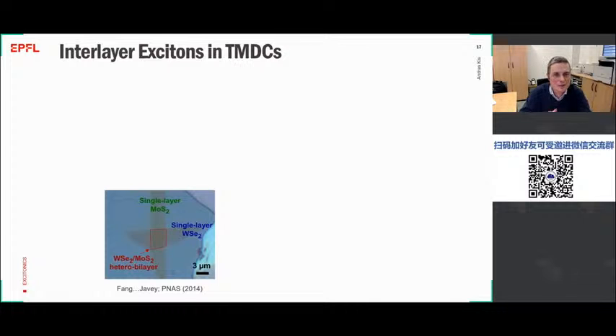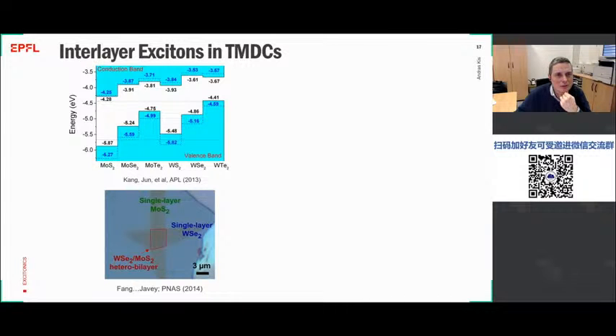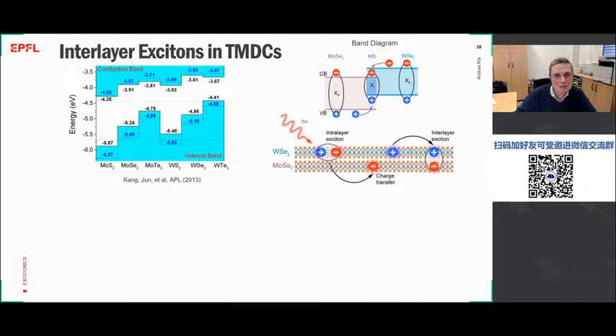In the case of 2D materials, this is very easy to do because the lack of dangling bonds on their surface means that we can take any one of those 500 or more 2D materials and put it on top of any other one of those materials. And when we do this, if we're talking about semiconductors, then we're also going to have, in certain combinations, different types of band alignment. And if we choose a combination of materials, like, for example, MoS2 and tungsten diselenide or MoSe2 and tungsten diselenide, then we're going to have a so-called type 2 band alignment.